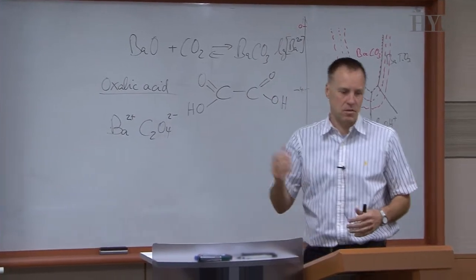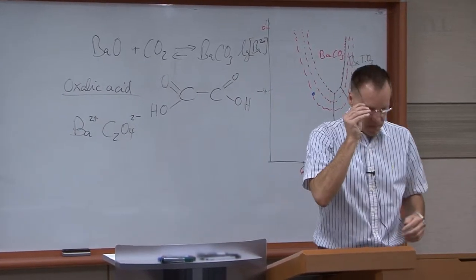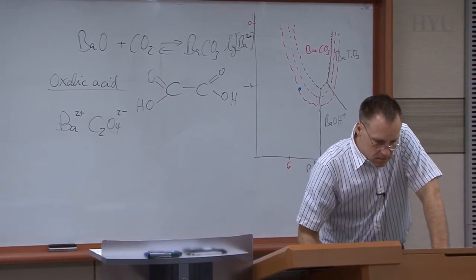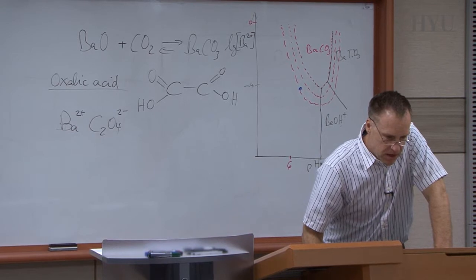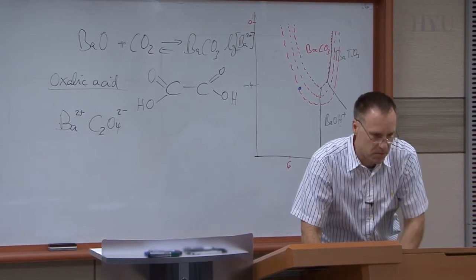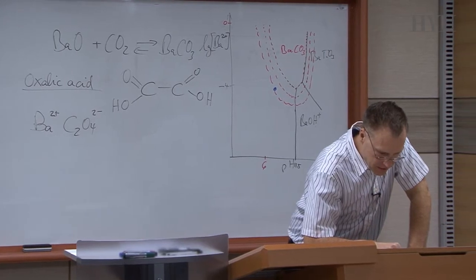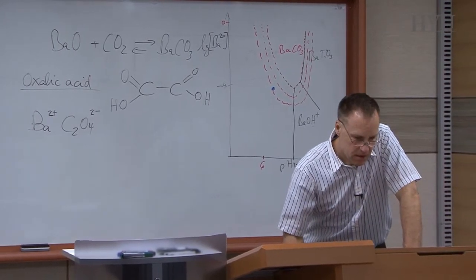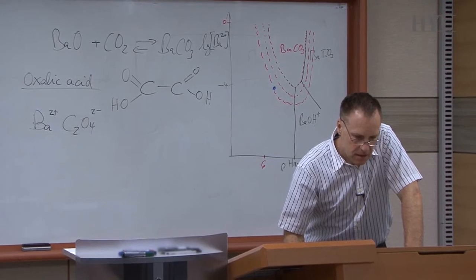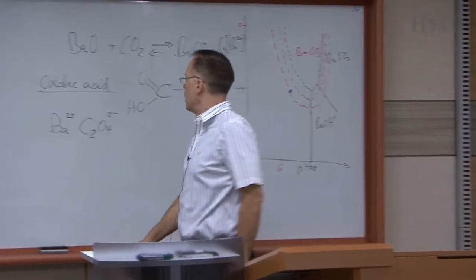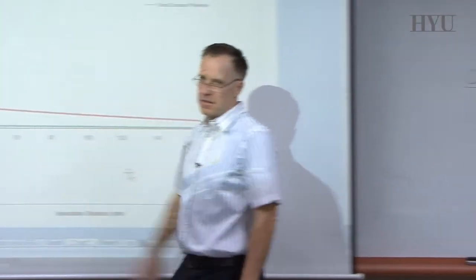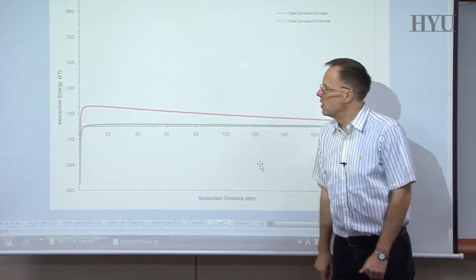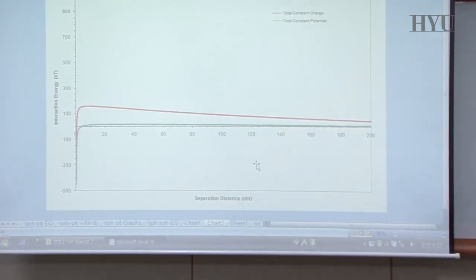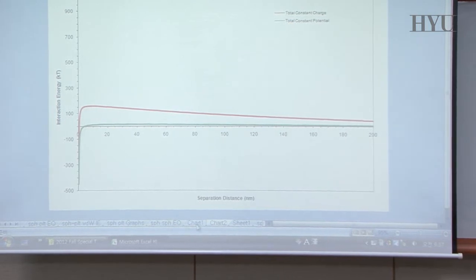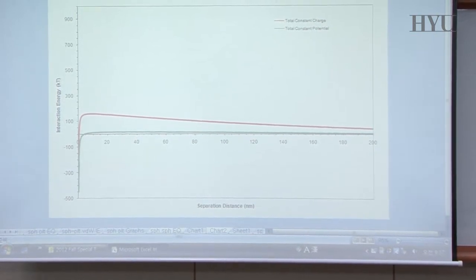minus 6 mole per liter or so. And let's just put this in here now, 10 to minus 6 mole per liter. That means we have to add another 2 zeros. Let's see. 1, 2, 3, 4, 5, 6. Yeah, 6. And now, working with oxalic acid, you get a nice long repulsion no matter with which curve. So with this, we can stabilize small particles. And of course, for large particles, this is for 50 nanometer particles, which you see is already much more challenging to get these potentials on than the large particles.